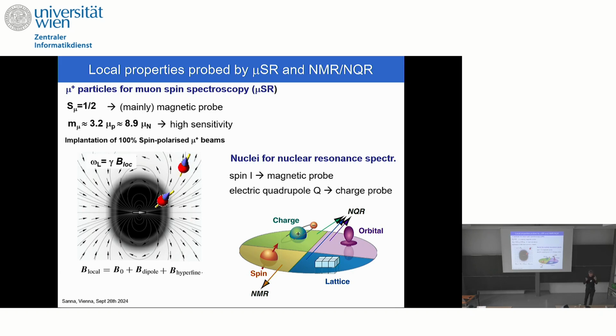The nuclei can do the same thing by considering the magnetic moment of the nucleus. In addition, if the nuclei have a spin higher than 1/2, then they also have an electric quadrupole moment. And if this is big enough, typically they are a very nice probe, not only for magnetic properties, but also for electric charge related phenomena. So we can probe both charge, spin, but also orbital and lattice properties, which are coupled to all these quantities. Okay, so this is the method that we are using.